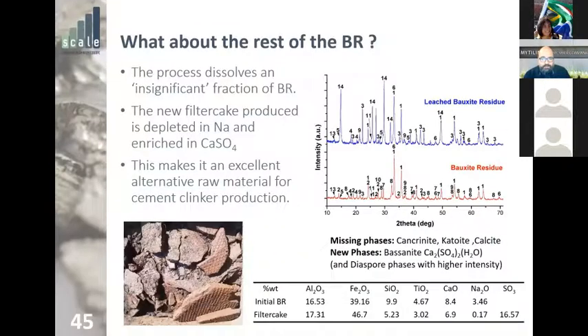And what about the rest of the bauxite residue? Our process doesn't dissolve any significant fraction of bauxite residue. In fact, as it precipitates calcium sulfates, it marginally increases the weight of the bauxite residue by 2%. But the filter cake produced is now depleted of soda and very highly enriched in calcium sulfates. This makes it a very interesting raw material for cement production.